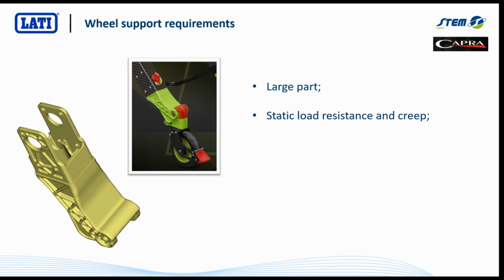Of course, it's got to have this static load resistance, but also a creep resistance as well. We talked about impact resistance. Dimensional stability is very, very important. So is it going to retain its shape post molding? Particularly important for two things. So firstly, of course, you've got those two components there that need to be able to freely move past each other. So it's no good if you've got distorted parts coming out of the molding. And then also you may be able to see here, so this section here of the part fits inside the carbon fiber tube of the leg. So again, it's important that we've got tight dimensional tolerances on this so that we can correctly fit this into the leg and connect it accordingly.